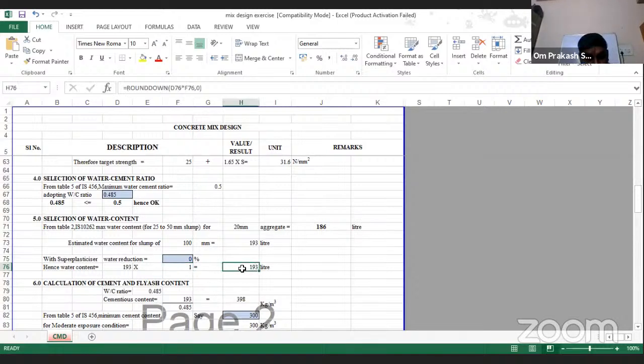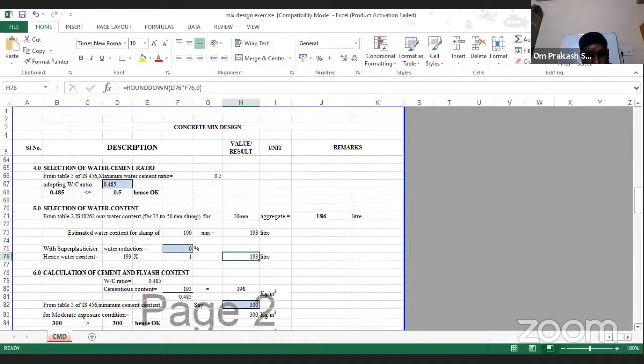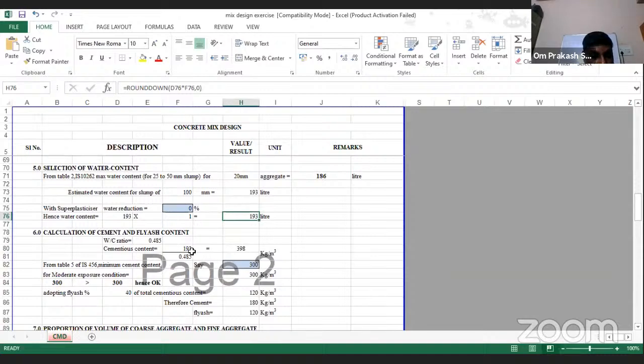And according to 193, if you go with the next row, 193 divided by the water cement ratio of 0.485, our cement content is 398, almost 400 kg of cement we need for M25. If we use super plasticizer and, let's say, reduce 10% water, our water content is 173. And for the same water cement ratio, our cement content is 357. Means almost saving of more than 40 kg of cement, or you can say almost 1 bag of cement has been saved with the use of super plasticizer.